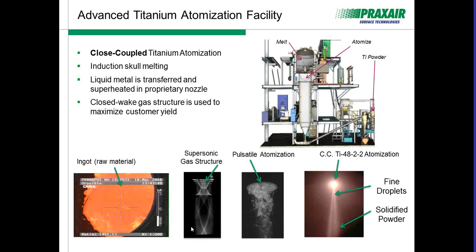This is an example of the gas structure that we would use. And as you can see here, this is actually a photograph taken using the Schlieren technology, in which you can actually see the different incident and reflective shocks. And here is going to be your Mach disk. I want you to imagine that this Mach disk actually exists in this image, because this is actually a video of close coupled gas atomization. And what's happening is the liquid's coming down, striking that Mach disk. It's then being recirculated up here, wetting across the landing, sheared and driven down towards the supersonic core. And then it's going through that double stage, primary and secondary atomization. As you notice, it momentarily chokes off the liquid stream, and then it starts again. And that's what it comes back to when we term this pulsatile atomization.